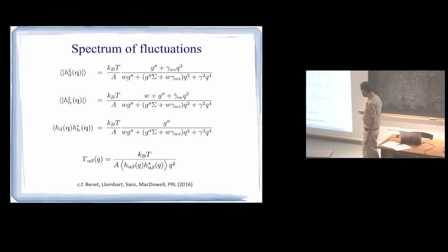How could I analyze this spectrum? I could do an experiment. From a scattering experiment, I can get right away these amplitudes in Fourier space. That's what glancing angle X-ray spectroscopy is about, to get the surface Fourier modes. Okay? And what I'm going to do is, instead of analyzing the surface Fourier modes, I am going to introduce this quantity, which is essentially the inverse of the surface Fourier modes multiplied by q squared. And this is actually a wave vector dependent surface tension.